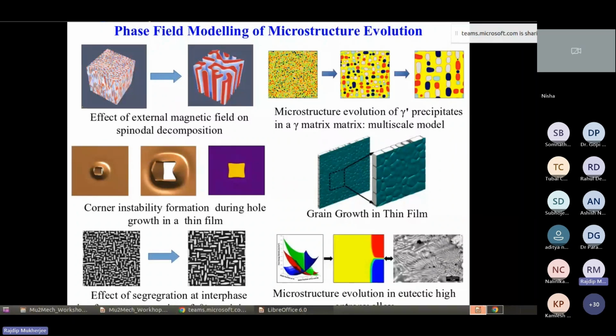And we study how these lamellar spacings vary with undercooling. If you cool much below the eutectic temperature, there will be a fine microstructure, and if you are just below the eutectic temperature, there will be a coarser microstructure. Depending on isothermal cooling or cooling rate, the microstructures will be defined. The compositions of the A-rich and B-rich phases depend on the phase diagram. You can get that data from Thermo-Calc or the CALPHAD approach, integrate it with this μ2mech model, and simulate this kind of eutectic solidification.